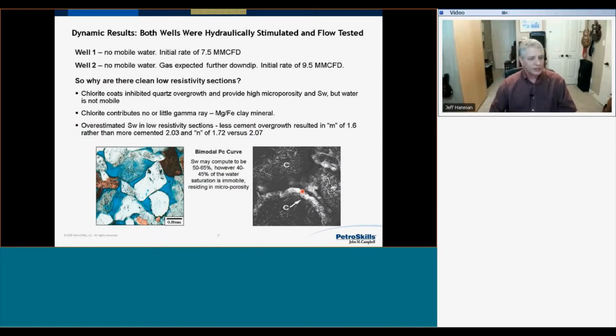Well, in this particular case, we actually have dynamic results because both of those wells were hydraulically stimulated and flow tested. The up-dip well, number 1, had no mobile water and had an initial rate of 7.5 million cubic feet of gas per day. Well number 2 also had no mobile water, so we may expect gas further down dip, and the initial rate was 9.5 million cubic feet per day. So why are there clean, low resistivity intervals? What is that all about if it's not fully water saturated and not water productive? What's happening?